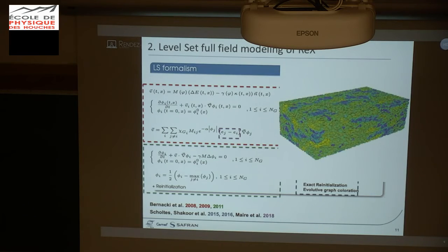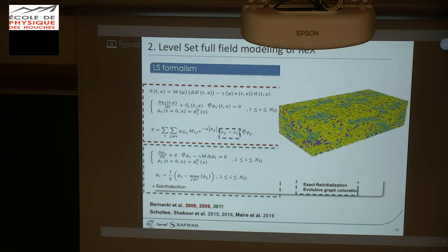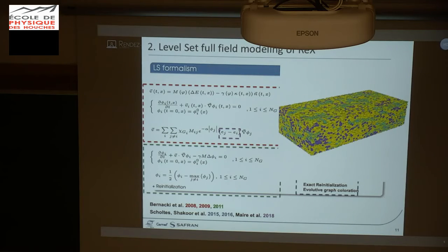And more recently, we have also improved our finite element framework to be able to use stored energy defined during deformation, by using a mean field equation for the prediction of the evolution of dislocation density, and most recently by also using a crystal plasticity formulation. With these elements, we are able today to simulate dynamic recrystallization evolution with a large number of grains in a polycrystal. I think that you will play with such simulations today in the DIGIMU TP.